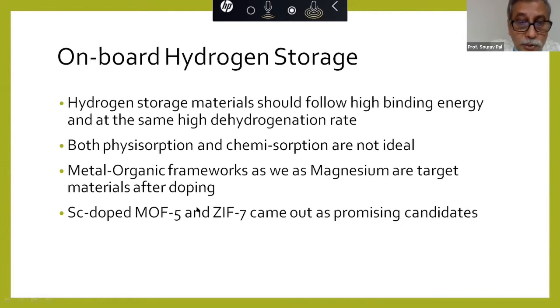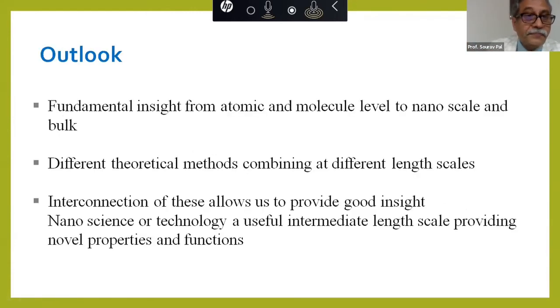ZIF, as all of you know, is zeolitic imidazole framework, and MOF is metal organic framework, ZIF 7. If you put scandium doped, that is very good. One of the reasons people used to put titanium doped, titanium was very well known for doping. But the titanium atoms started clustering among themselves. So there is a titanium-titanium bond, which did not allow the MOF or the ZIF to absorb a large amount of hydrogen. Scandium does not cluster, and this is something that we have analyzed in our calculations. And that is the reason scandium doping worked out very well.